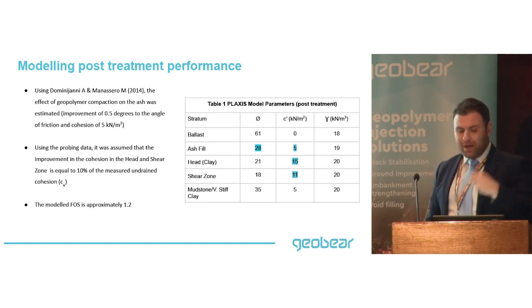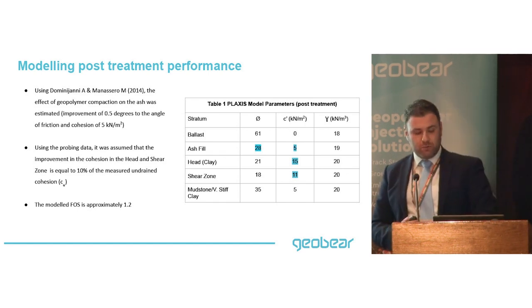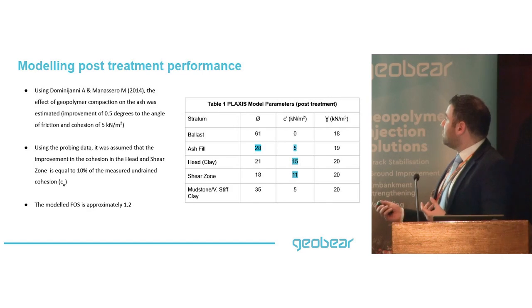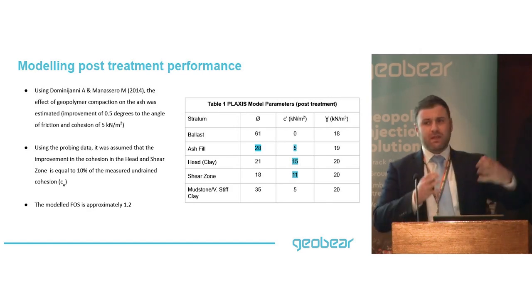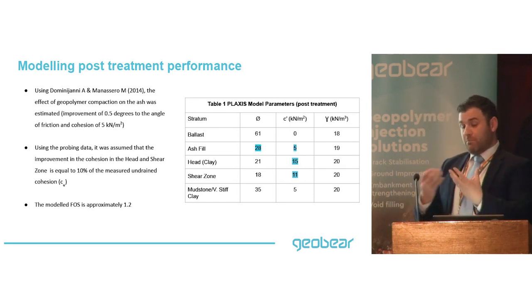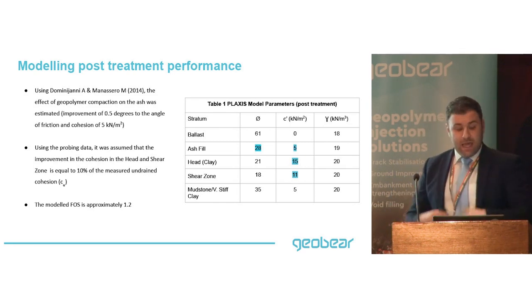So what happened to the ash, what happened to the head, and what happened to the shear zone? These are the highlighted parameters, the ones that have actually been affected by the improvement, and that was quantified from the probing data. So we've taken that and carried out the analysis.